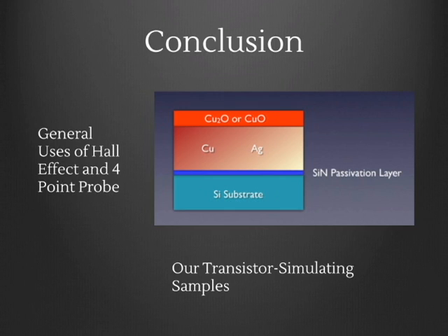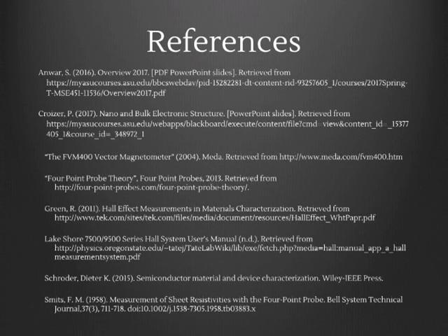In this video, you have heard about two essential electrical characterization techniques. You now understand their modus operandi and the devices themselves. Both techniques are used to derive the conductivity of a sample. With the Hall effect measurement, data can also be obtained about the mobility of carriers. In this presentation, you heard as well about the electrical testing of microwaved annealed samples, which simulate thin film transistors. This electrical testing revealed that the sample annealed for the longest time had roughly twice the conductivity of the unannealed sample. It can be inferred that this annealing was successful in partially limiting delamination of the sample, resulting in better contact and better conductivity. Thank you for listening to this presentation.